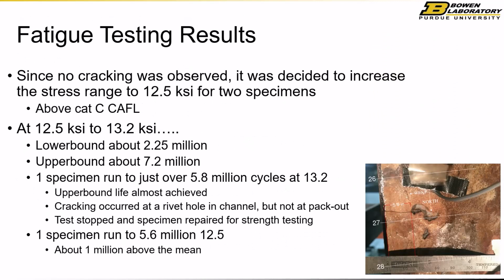But that wasn't good enough for us. We said, okay, well, we've done all that, let's jack up the stress range. So we took specimens and ran it up to 12.5. Why 12.5? Well, category C is a threshold of 10. Riveted members for evaluation in the MBE were allowed to use category C. So we said, well, let's go above category C and see what happens. And it's hard to dial in perfectly. So the number is 12.5 to 13, lower bound of 2.25 million up to 7 million.